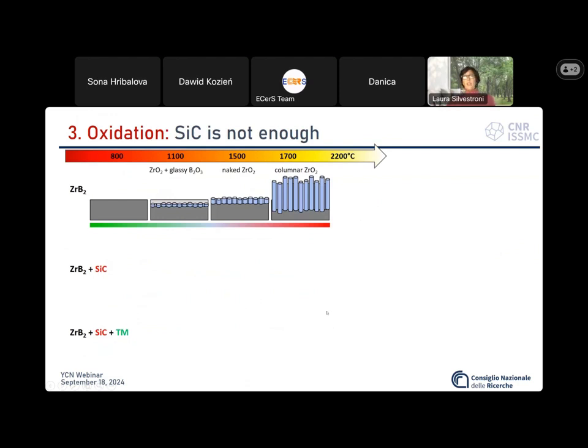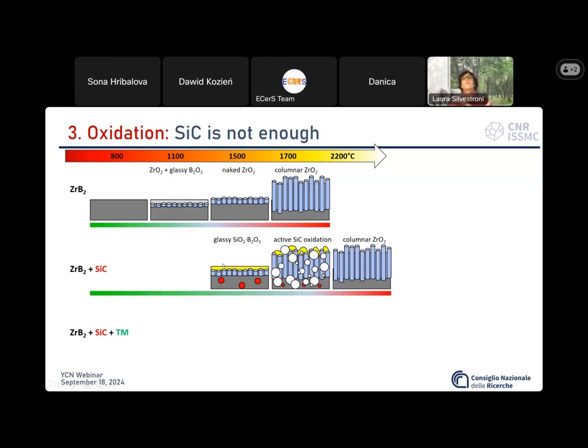Let's move now to the oxidation of zirconium diboride, which is again quite a complex topic. Zirconium diboride alone doesn't really work because it forms boron oxide, which is volatile at definitely too low temperature for such materials. But at higher temperature, it leaves just a naked porous zirconium oxide skeleton, which is not really sufficient. The addition of silicon carbide prolonged a little bit the lifetime of the zirconium diboride, but still, as we move above 1700 degrees C, we start having problems of active oxidation in the subsurface, and again, we don't achieve the 2200 that could possibly be achieved in the hypersonic application.